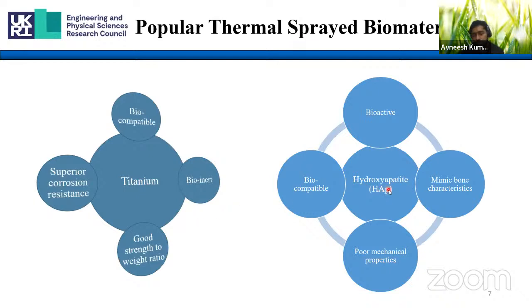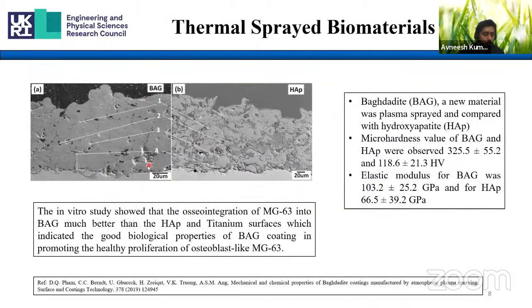On the other hand, hydroxyapatite is a mineral which mimics the bone characteristics. It is a calcium phosphate compound. It is very biocompatible, but it is also bioactive in nature, which means that it helps in bonding between the bone and the implant surface. It also helps in the growth of cells onto these implant surfaces. But the problem with this material is its poor mechanical property. So in view of this, Professor Christopher has already discussed in his talk that they have developed some coatings of calcium silicate compounds, which is bagdadite, using plasma spray, and they have also prepared some hydroxyapatite based coating, and then they compared both coatings in terms of their mechanical performance and biological performance.